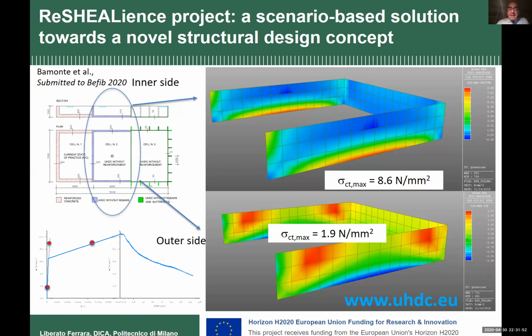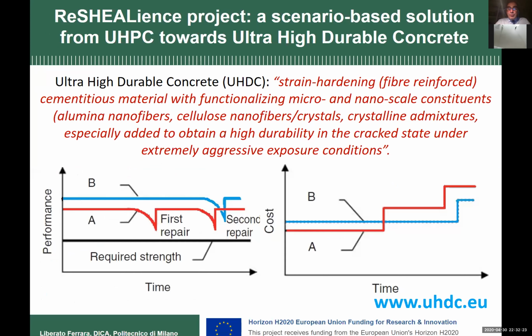Remember that we moved from 40 centimeters in the original solution to 6 centimeters. So there is a saving of quantity of material of more than 6 times. And we have no reinforcement at all, but we have the fibers inside this material. According to the mix design I showed in the previous slides, there are 120 kilos per cubic meter of steel fibers.